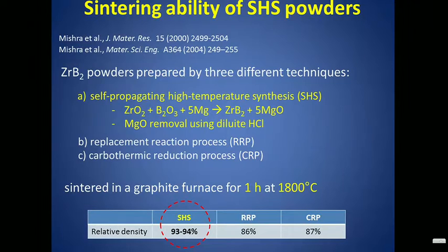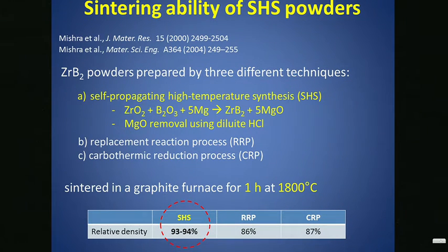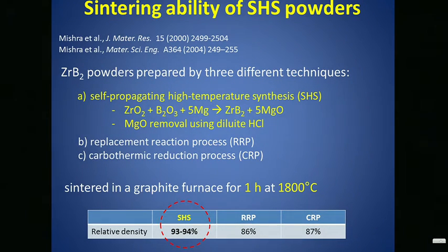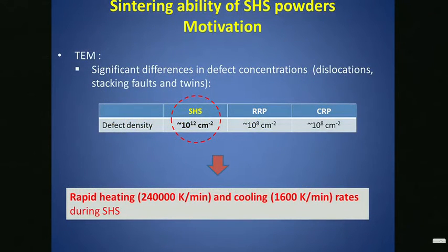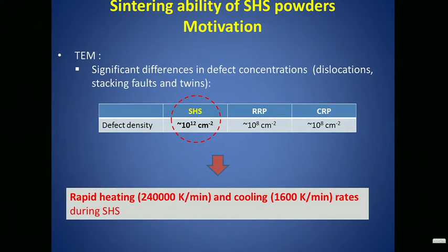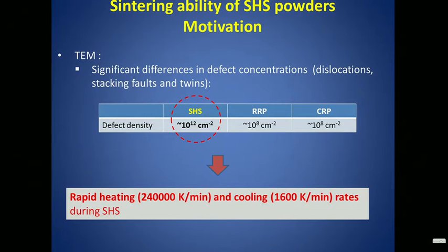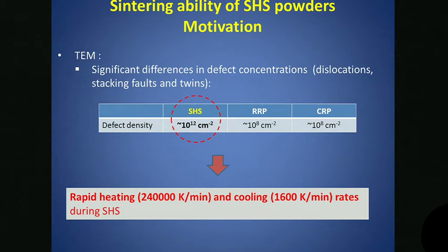In the early 2000s, three different techniques were tested, and at the very end, all the powders produced through these techniques were sintered under the same conditions. What you get is that the relative density of the material at the end is much better with SHS with respect to the other technologies. The reason is that if you look through TEM at the defect density, SHS technology provides a much higher concentration of defects. This is due to the fact that you can get heating and cooling rates of such values, which are not reachable by other techniques.